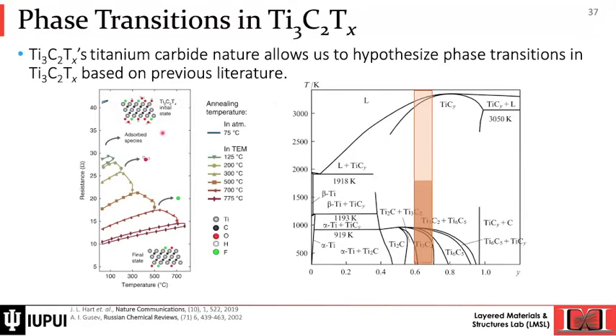First of all, if we heat treat MXene, if you want to go to high temperature for every material, if you want to avoid oxidation, you need to use an inert atmosphere or vacuum. Now, if we run it under inert atmosphere and vacuum, we can remove the surface termination. We can gradually, up to 700 or 800 degrees Celsius for Ti3C2, remove the OH, fluorine, and oxygen from the surface of MXene. Then it becomes a titanium carbide phase diagram structure.